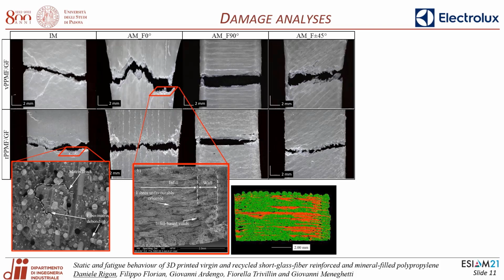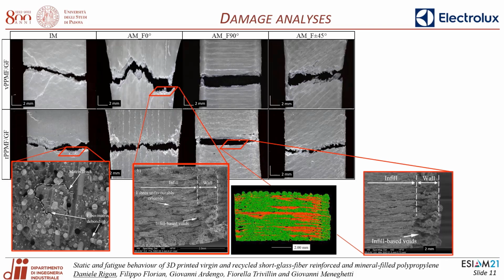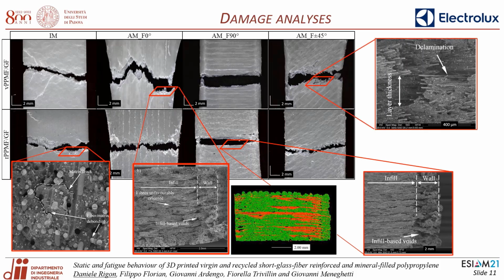In the case of virgin F0° and recycled F0° samples, the fracture surfaces were planar, normal to the loading direction, and located at the interface between adjacent filaments. Finally, macroscopic fractures, almost perpendicular to the loading direction, were observed in the case of virgin F45 and recycled F45 specimens, as shown in the last column.